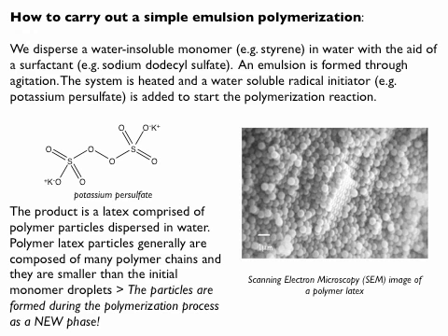So this is initially rather surprising. Yeah? So either the density of polymer is so much larger than the density of monomer that you get a massive volume contraction. Is that true? Well, the density of polystyrene, for example, is 1.06 relative, and the monomer is 0.909. So you get about 20% volume contraction. So on radius, that would be, whatever, the cubic root of that. Yeah? So that would not account for such small particles. So that is out of the window. So that basically means that throughout the process, I have to form another phase. Something is happening that we didn't know initially that produces those small particles rather than polymerizing the large monomer droplets.